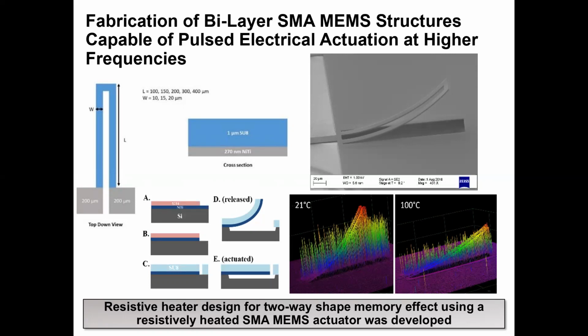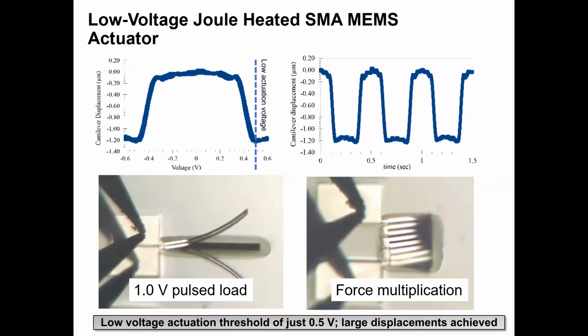These experiments helped to confirm the two-way shape memory effect in this new device design based on SU8 and NiTi. From here, the next steps were to characterize the electrical actuation of the device, starting at low frequencies and progressing towards higher actuation frequency to explore how well this design would facilitate fast and reversible actuation. So the figure in the upper left plots the cantilever displacement versus the applied voltage. These curves were experimentally generated.